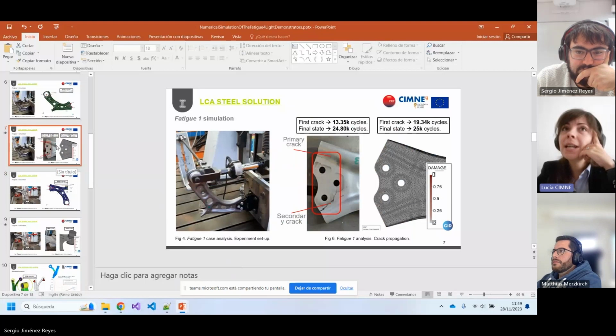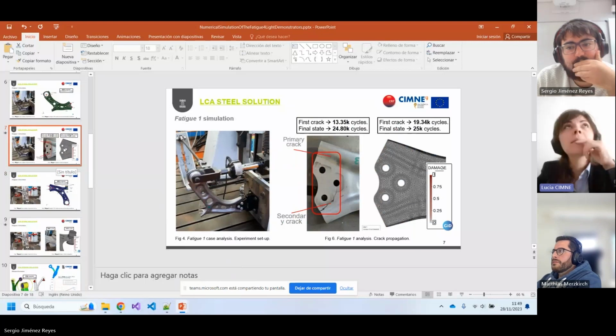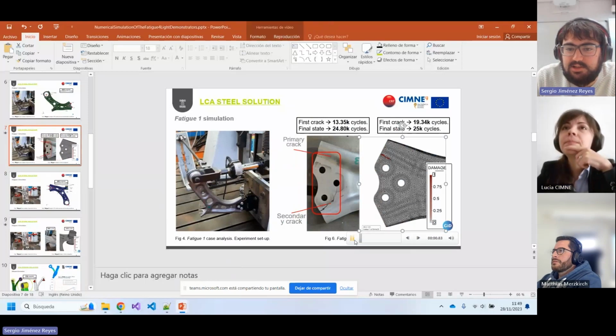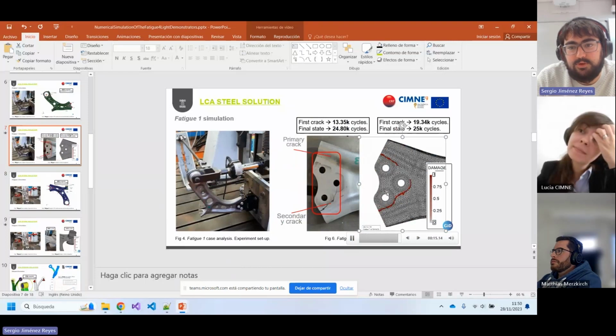And for the purely fatigue case, it took longer. We spent, I think, nearly 2 days. Just initiating. Up to this point, it's really fast because you jump from the second phase in the material towards the propagation of damage. This is really, really fast. The problem here is that you need to propagate the crack, then initiate the propagation and propagate the second crack. That's why this type of simulation really took a long time, because from that point on, you are already always in the inelastic domain.